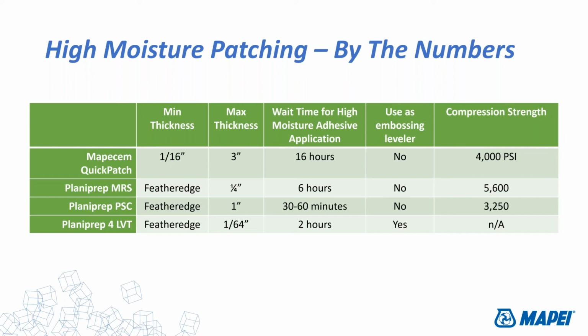Planiprep PSC, the one we just introduced or what we're talking about today, is 1 inch to feather edge, very fast drying, 30 to 60 minutes. So that's going to be well received by the installer base, the contractor, no longer having to wait for high moisture adhesive applications. You can't use this as an embossing leveler, and it's still got a pretty good compression strength, which is above that 3000 minimum requirement for ASTM F710.